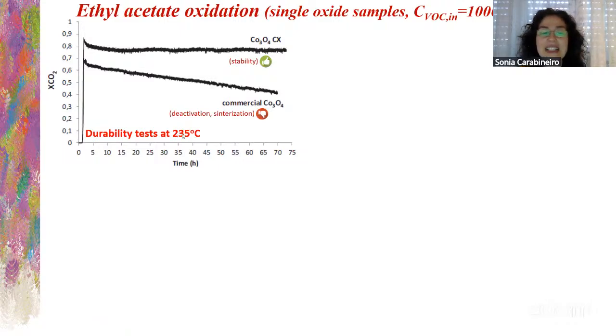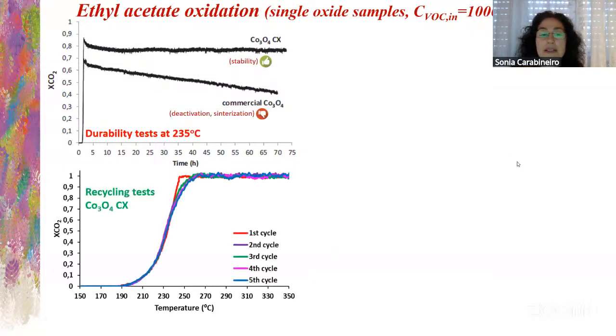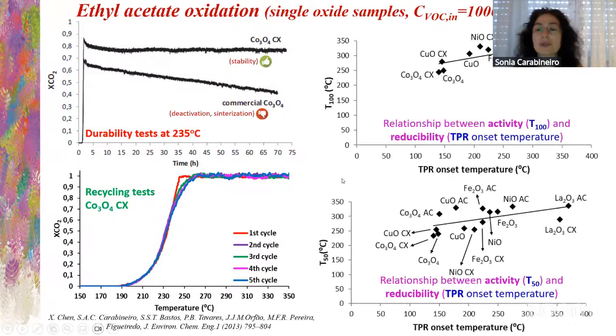So we see here at 235 up to 75 hours. We saw that the samples prepared with carbon aerogel had a good stability. It continued, while the commercial sample started to decrease, deactivated. It was due to sintering of the particles. We did recycling tests, and from the first cycle to the other cycles there was a little bit of loss of activity, but even so, it was not so bad. So it was quite durable.